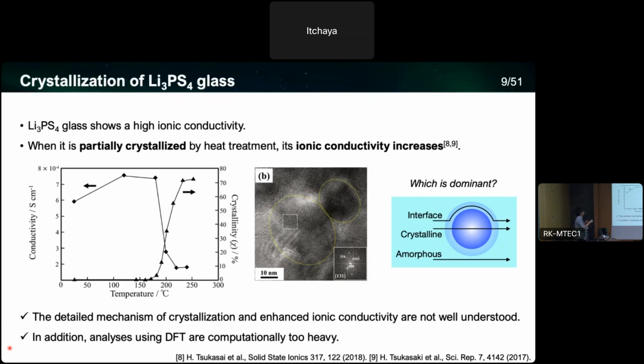Interestingly, experimentalists also found that when the glass Li3PS4 is partially crystallized by heat treatment, the ionic conductivity of the partially crystallized Li3PS4 increased. This is the graph that experimentalists presented. The vertical axis shows the ionic conductivity, and the vertical axis at the right-hand side shows the crystallinity of the partially crystallized Li3PS4. By heating the material, the crystallinity increased. Along with that, the ionic conductivity increased at the beginning. But when the crystallization further proceeded, the ionic conductivity decreased. So this peculiar phenomenon was observed through the experiment.